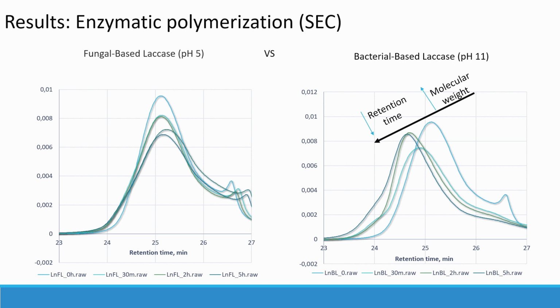I will start with the molecular weight distribution between 2 different treatments with 2 different LACCASEs. The main difference is that when we apply the bacterial-based LACCASE with higher pH, we can see that the lignin peak is inferior with the treatment time. By this means, we have a lignin with higher molecular weight, showing the polymerization. So the next step was to study why we have different behaviors for the LACCASEs.